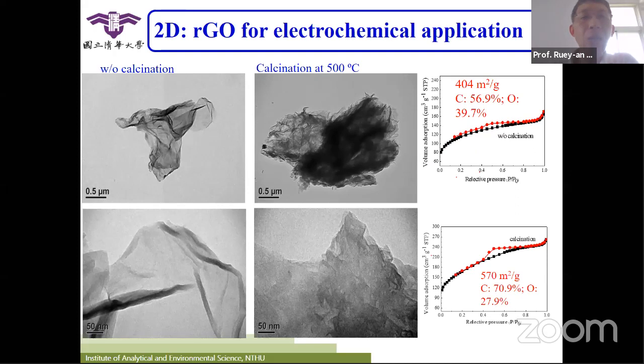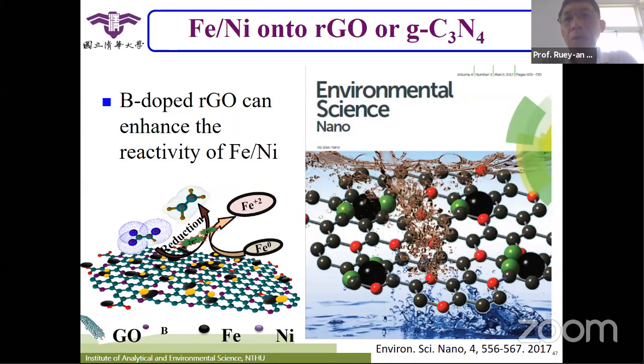So this one is actually the case for graphene in reduced graphene oxide. So we can see the sheet here. The surface area is around 404 and 570, which is relatively high. We immobilize some metals on the surface of reduced graphene oxide, and you can see that they are dispersed on the surface very well.